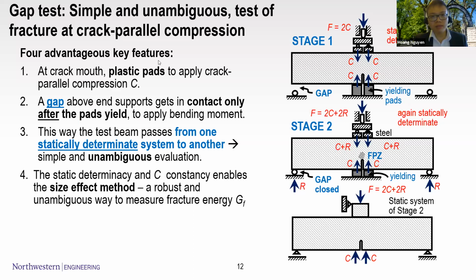So we know something about quasi-brittle materials. So how to apply the crack-parallel stress and see its effect? We came up with a new loading configuration which is called the gap test. This is a simple and also unambiguous way to extract the effect of the crack-parallel stress. Several features can be listed here.